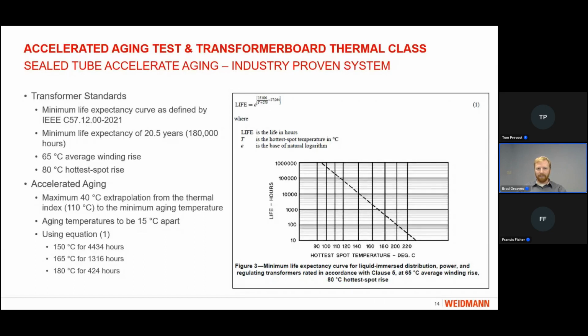So when we look at the minimum life expectancy curve and try to relate it to an accelerated aging test, we look at a maximum of 40 degrees C extrapolation from the thermal index, which again is 110, to the minimum aging temperature. The standard requires that we have aging temperatures to be 15 degrees apart. So using Equation 1 from this standard, we can define our three aging temperatures at 150, 165, and 180, and a corresponding aging period to achieve the minimum life expectancy.